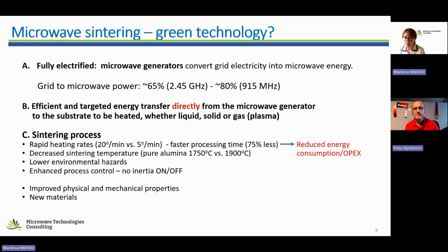I know all of these parameters. Okay? And third parameter related to the sintering process, in everything that I read, and you also mentioned that, rapid heating rate. So we have something like 20 degrees reported per minute versus 5 degrees per minute in conventional. So that means it's faster processing time. It's 75% less time. That, of course, goes to reduce energy consumption and OpEx.